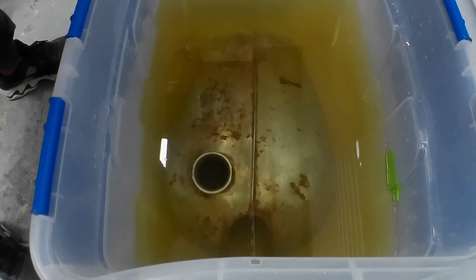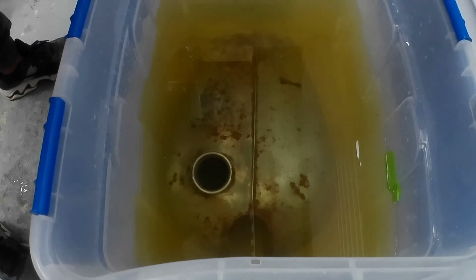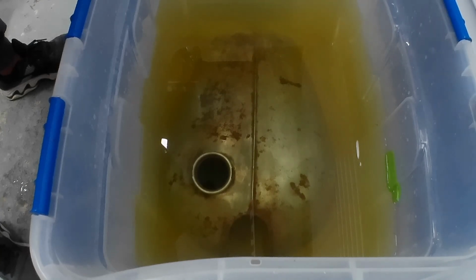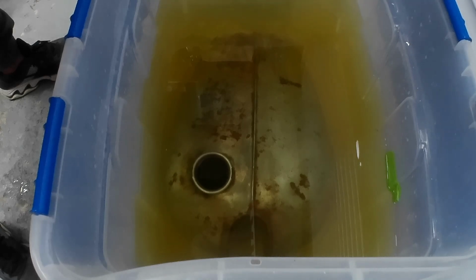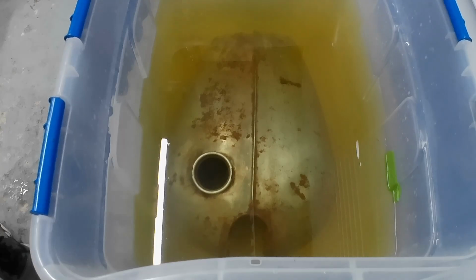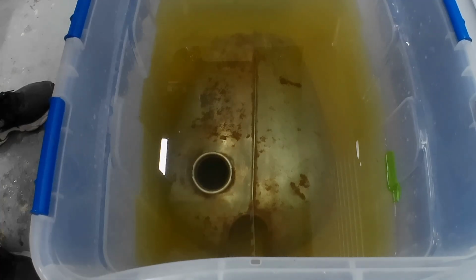That's what we want. The only drawback is that there are iron ions in the good steel that we want to keep, and if we have too strong a solution or we leave it in for too long, we're likely to get an etching of the surface. And this is actually made worse: the more metallic salt we get in the acid, the more likely it is to etch. So it's a bit of a double-edged sword, really. But as long as we keep an eye on it, and don't leave it in there and go away on holiday or anything, it's quite acceptable, really.